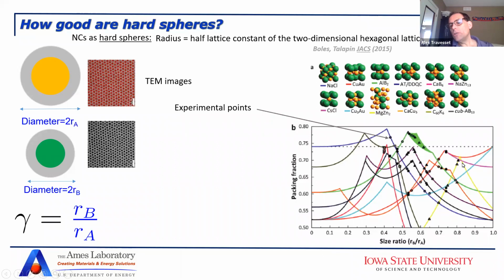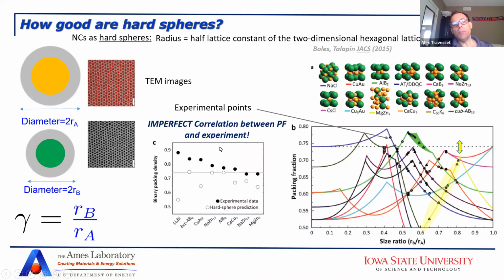Number 2 is that, if you take this seriously, in this particular case, if those are packings of hard spheres, the packing fraction becomes very small, 0.5. That is a very open lattice, and you should be skeptical about the stability such a lattice should have. This is too much open space. So basically what we see is that there is an imperfect correlation between packing fraction and experiment.